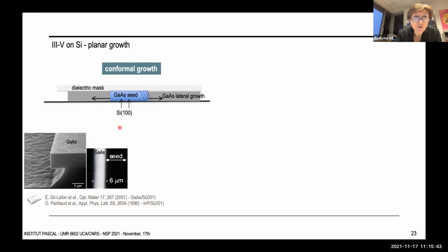And this is evidenced or revealed by the luminescence of the conformal gallium arsenide layer here, of which front plan is shown here. The efficiency of this refining effect is again demonstrated with the conformal heteroepitaxy of indium phosphide from gallium arsenide seeds, where you can see that after the zone where the seed dislocations glide into indium phosphide, then you have a defect-free indium phosphide stripe on silicon.